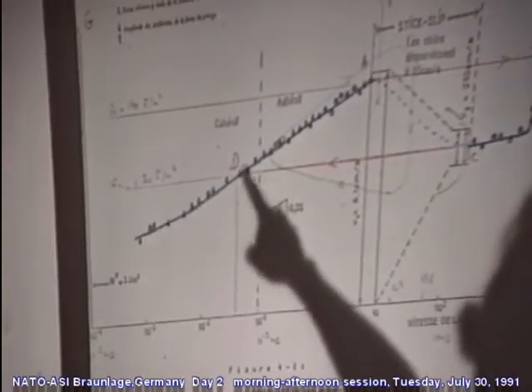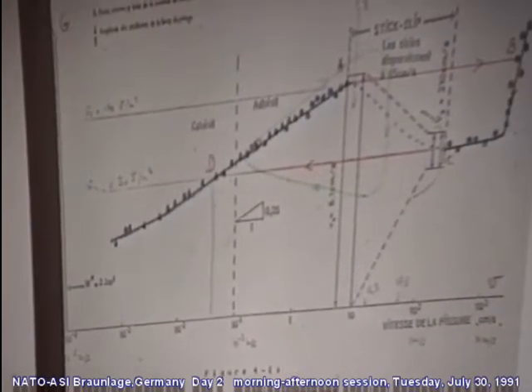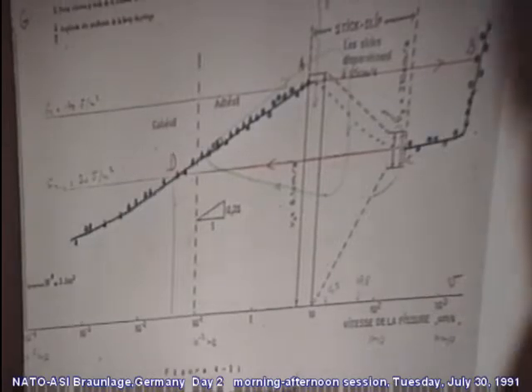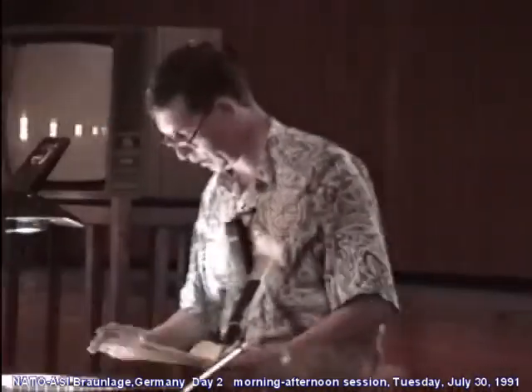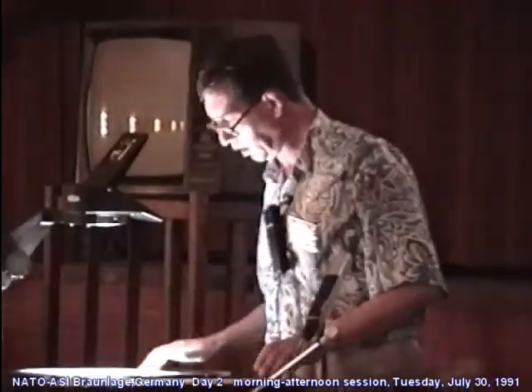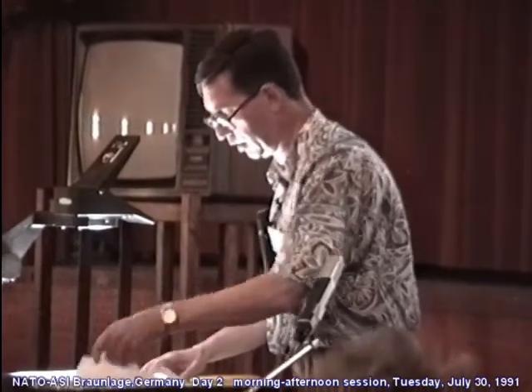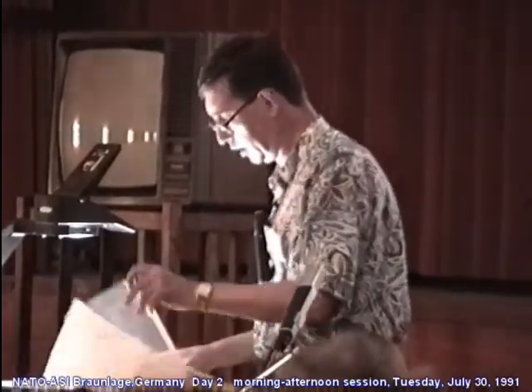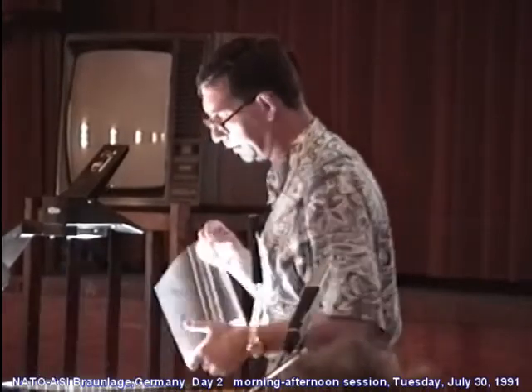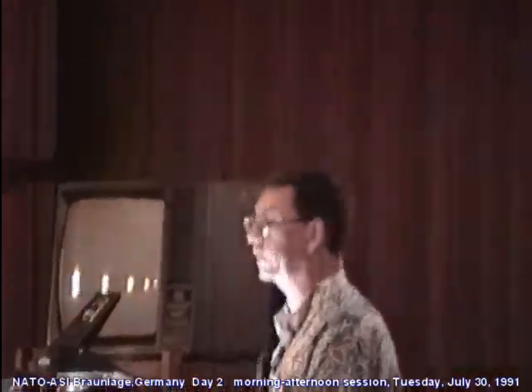It may be observed that the separation, the rupture, is cohesive until this limit, and adhesive below. So a mark is left on the band at each cycle, and you can measure the frequency by the marks left on the band. In the cycle I have just described, most of the time is spent on the branch with low velocity.